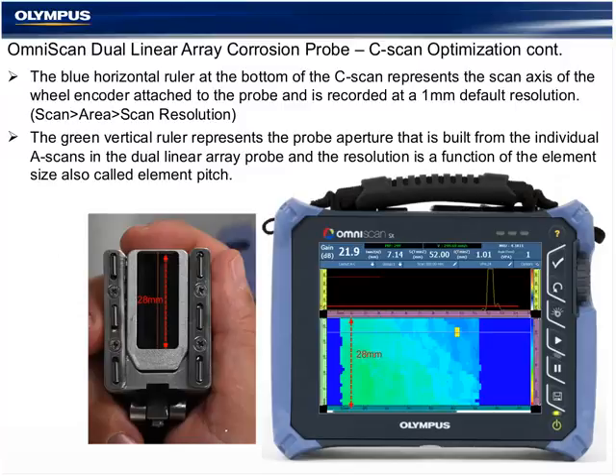So the probe face in a single line scan represents the A-scan first to A-scan last stacked vertically. This axis at 28 millimeters represents the entire length of the probe using the 5-element configuration. And the green vertical ruler for a 0-degree linear scan is volumetrically corrected, so it's millimeters to millimeters, whereas in an angle beam inspection, those of you that do OmniScan, an angle beam shear wave weld inspection, would normally be seeing the C-scan in focal laws or apertures here.